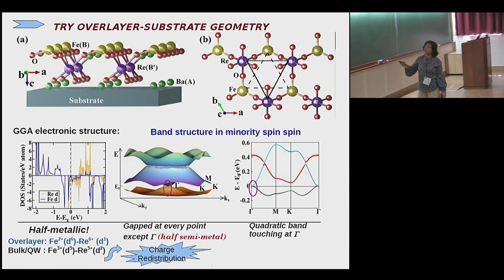That means we have a substrate of barium titanate on top of which we had two layers of this double perovskite, which consist of a rhenium layer and an iron layer, and in between a BaO3 layer. So in this configuration, the iron is in highly reduced connectivity. Instead of having 6 oxygen, it will now have 3 oxygen, and therefore the site symmetry at the iron gets reduced from the octahedral symmetry to a C3 symmetry, and that imprints very strongly on the electronic structure of